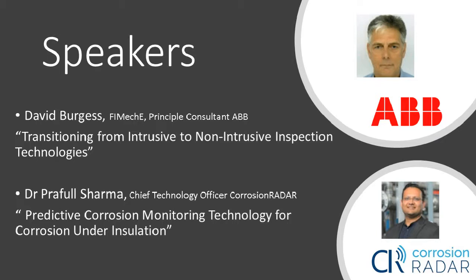I'm not sure I can fully answer it, but obviously if there's a corrosion mechanism that is particularly aggressive and not predictable, then the process, whether it's risk-based inspection to API 581 or NII to the recommended practice I showed, may define extensive coverage of non-destructive testing from the outside. That's really where you need to compare the benefit that you will get, because you might find that it's a very large vessel and you've got to scan the whole external surface because the process says so, and then it might not be the best method to go forward. So in a way, that's part of your assessment. Even though it might be safe to do so, you need to look at the economics as well. Hopefully that answers that.